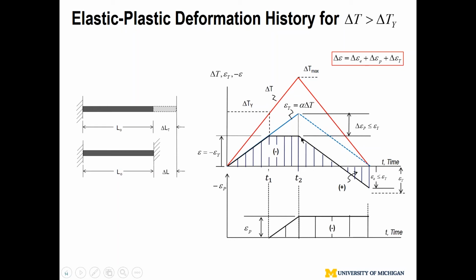In friction stir welding, we work at a forging temperature. That means this temperature can be easily exceeded. That means I'm going to have a reduced stress. I'm going to have a permanent effect. So keep this in mind. Even though this is a very simple exercise, we can establish a critical temperature we call delta Ty. That stands for the yield temperature, the temperature increase to yield steel under fully restrained condition.